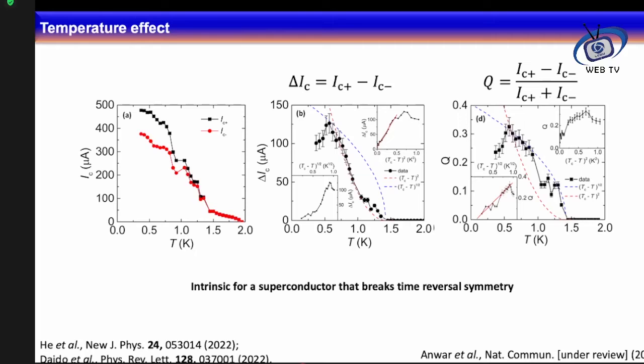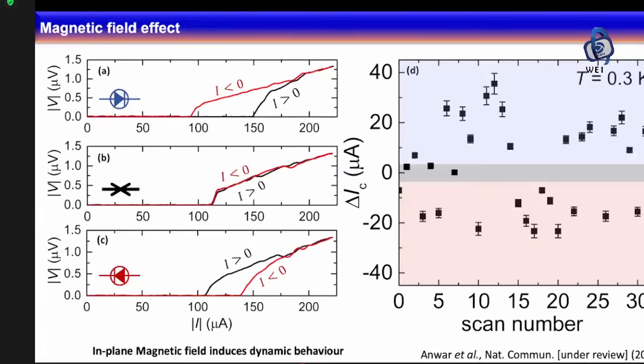So then, whatever I showed you here about the non-reciprocity of my devices is without any applied magnetic field. But still, you can try, just switch over here, then you can also try to understand what will happen if you apply the magnetic field. If you apply the magnetic field, then in our devices, we observed that the critical current is not stable. It is quite unstable. And then I switched off the magnetic field. But then my device was in this configuration.